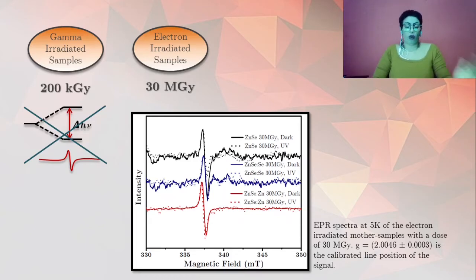None of the most common defects in zinc selenide, such as isolated zinc vacancies or complexed zinc vacancies, have the characteristics of the line observed in the samples. One hypothesis for the origin of the signal is that it could be related to a simple shallow donor, but the levels for shallow donors in zinc selenide are too close to the conduction band, making it difficult to observe by EPR due to a limitation of the technique.